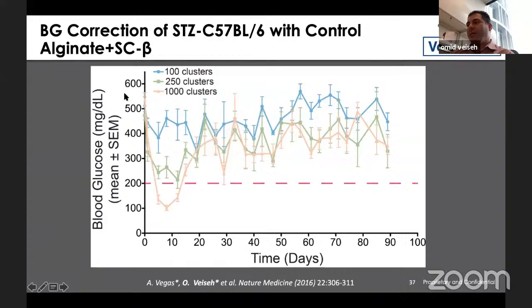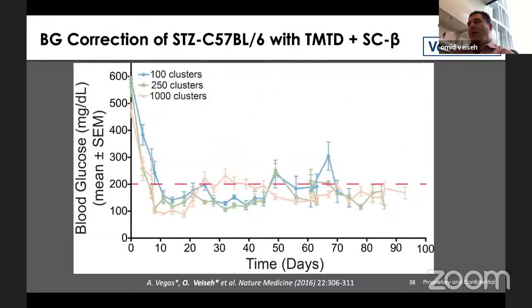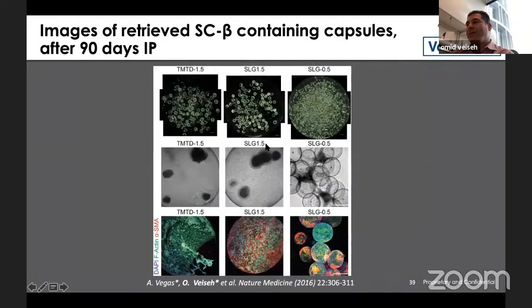When we implanted them without the coating, with the material that is essentially what's considered to be clinical grade, available, and had been to clinical trials, it only worked for a couple of weeks, very similar to what Lim and Sun saw in their studies. When we have the modification, we're able to see a much more durable response because the material is no longer getting fibrosed, and so the cells are able to last much longer. In this case, we went out for 90 days. And this is what the capsules look like when we retrieve them.